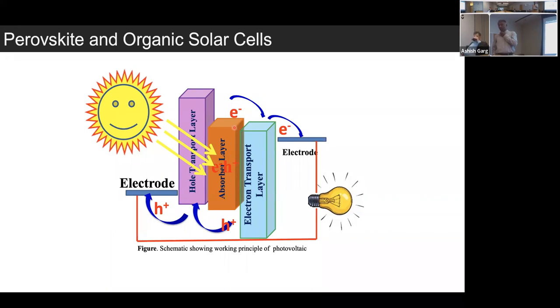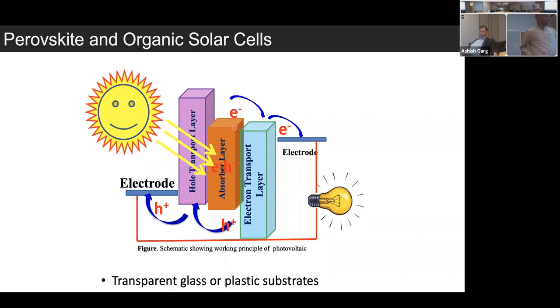The major issue with these two technologies is that their stability is very poor. They don't last in the ambient, depending upon where you are. If you're in India in monsoon season, they don't even last for a couple of days, but in summer and winter, they might last a little longer. Another problem with perovskites is the presence of lead, which is an issue in their commercial realization at the moment. The good thing is that you can make these on either transparent glass substrates or plastic substrates, which enhances their application potential, especially for organic solar cells. And their processing temperatures are generally very low, which is again a very positive point from the perspective of thermal budget.